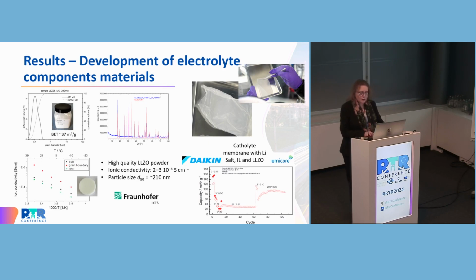Here you can see that we have an easy to fabricate membrane with the mixture of PVDF and LLZO. And this material has been tested in half cell with NMC 622 versus lithium metal at 25 degrees. The cycling has been done up to 100 cycles at 0.2 C as cycling rate. So it's stable, and the result was very interesting in this case to continue with this formulation for the full cell.